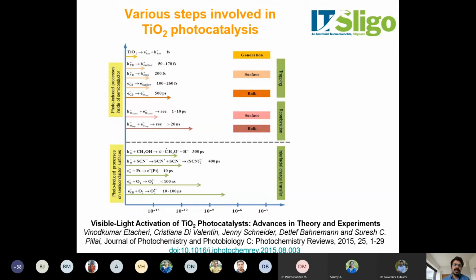So if you look into the time scale, the generation happens at the level of femtoseconds. Recombination happens in picoseconds. Okay, so there is some time limit. But trapping also happens in femtoseconds. So if you apply a trapping agent, it will be much faster than the recombination. So we can effectively use different types of trapping agents to improve the reaction process.